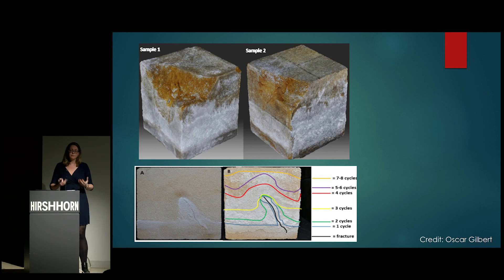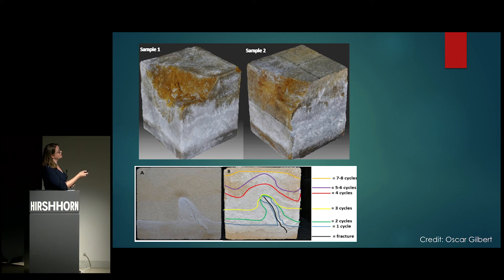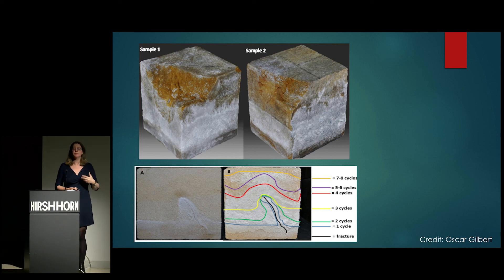As a geomorphologist, I study stone weathering — how stones respond to environmental stresses. As far as I'm concerned, the bullet impact is just an extremely rapid deterioration process. We saturated blocks with a saline solution and found that salt goes absolutely bananas for the cracks caused by bullet fractures, meaning that where we have bullet fractures running through a heritage structure, it becomes a lot more vulnerable to environmental deterioration in the long run. You can see how that salt moves preferentially through the crack formation associated with the ballistic impact.